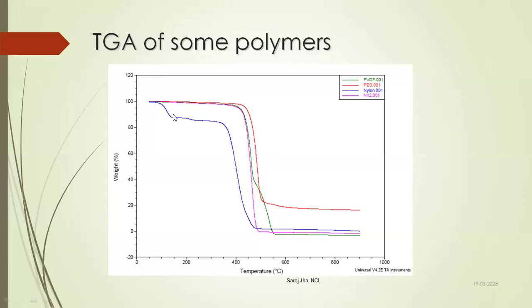If you concentrate on the blue curve, you can see that there is one stage below around 170 degrees centigrade. What does my TGA curve tell me here? That there is either water in my sample or some organic solvents which are getting evaporated below 150 or 160 degrees centigrade. Then again, there is the onset of degradation and completion, giving me no residue. The green curve shows me that my sample has a 2-stage degradation.